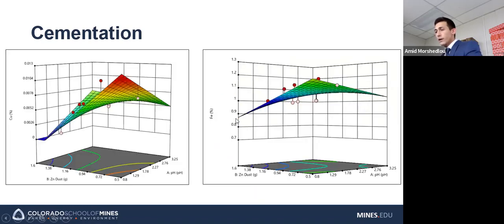So right here, we have the same response surfaces. We have copper on the left, iron on the right. And this is grade in the solution afterwards. In both cases, what we want to do is minimize the grade. We want low copper in solution and low iron in solution because we're trying to take it out of solution so that we can take those elements and feed them in somewhere else while we take that solution and recover the zinc from it, free of copper and iron.